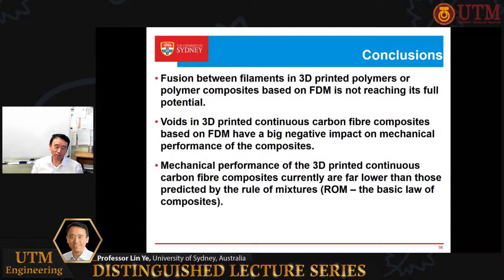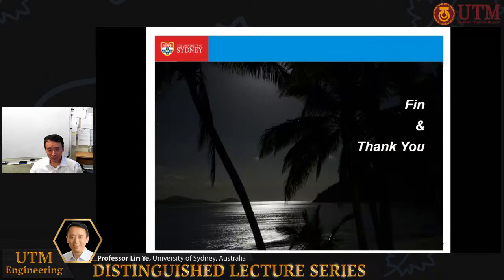So we say the void in the composite has a very big negative impact on the mechanical property. The mechanical performance of any kind of 3D printed or additive manufactured composite material is currently far lower than that predicted by the rule of the mixture, which is the basic law of composite design. That means we're still not yet close to a good quality 3D manufactured composite. It's still a long way to go. I think that concludes my presentation. Thank you for listening. Thank you for your attention.